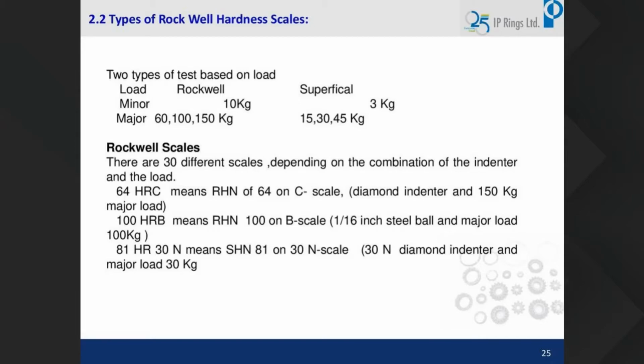Mostly this Rockwell is used for testing the final product or annealed parts. Also you can check where the surface area is very small, and where we cannot use the Brinell hardness, we can use Rockwell as a tool for checking. For the superficial hardness, generally we check piston ring steel wires. Either they give the requirement in HRC or in superficial hardness like HR 15N, 30N, 45N. Here also you have the N scale and T scale. If you are using the diamond indenter, it is the N scale, and if you are using the 1/16 inch ball indenter, it is called the T scale. There are many applications, more than 30 different scales available with this combination of loads. We can check both ferrous and non-ferrous using the Rockwell hardness tester.